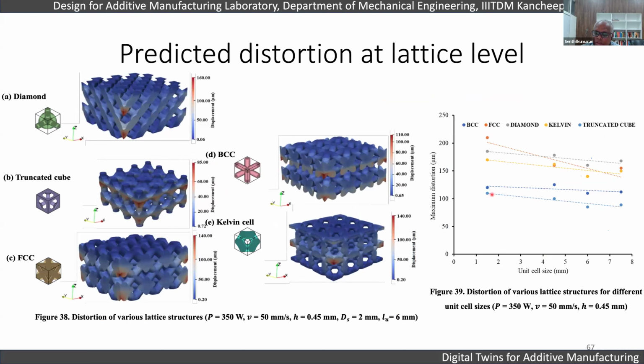It has the lowest distortion, consistently along all the unit cells. But if you see FCC, at the higher unit cells its distortion performance was much lower compared to other shapes, right? So these are important observations that we made based on the simulations that we have had.